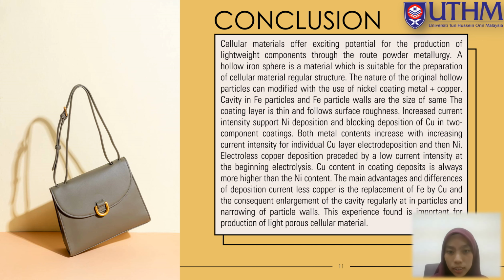Increased current intensity supports Ni deposition and blocks Cu deposition in the composite coating. Both metal contents increase with increasing current intensity for individuals. Cu layer electrodeposition and then Ni. Electroless copper deposition is preceded by low current intensity at the beginning. The Cu content in the coating deposition is always higher than the Ni content.